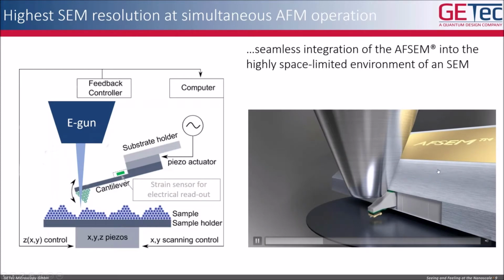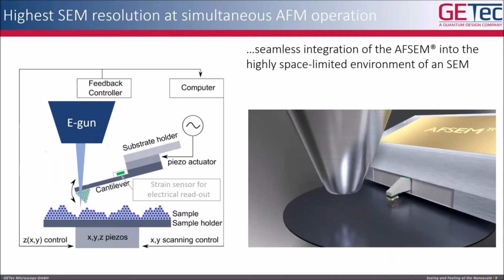We can really, with the core stage, move the AFM scan head directly below the pole piece of the electron gun. We can start the AFM scan, and we can even do that in parallel with the SEM, so you can really have the SEM running and really see what the cantilever is doing on your surface while you're making the AFM inspection.